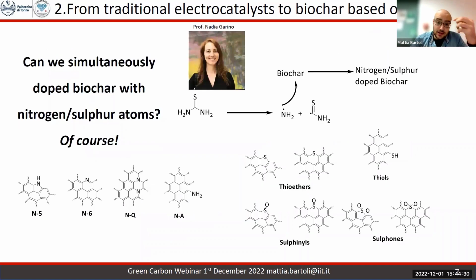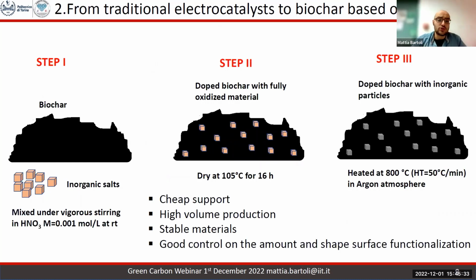So we use this approach, and with the collaboration of Professor Nadia Garino that you can see in the picture, we try to insert into the biochar a lot of heteroatoms, because those heteroatoms could be a boost for electrocatalytic activities. Moreover, the introduction of nitrogen and sulfur could be performed by using thiourea, which is quite cheap. But in this case, cheap means good, because it's a reagent that could insert inside the biochar structure the heteroatoms that we need. So the final material is a highly engineered material that contains nitrogen and sulfur, more than pristine char produced from sludges, for example, with a control on the inorganic components that are another key parameter for this field of application.